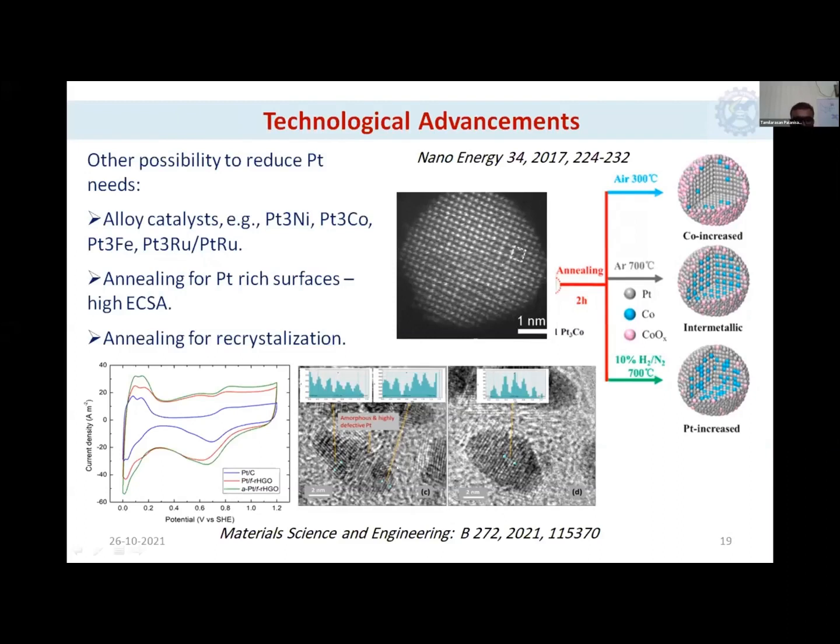But while we anneal in situ, frame by frame, we observed what's happening to the particle. It actually turns into a single domain particle. Okay, it has a single crystallite. But if you see here, before it has more than two crystallites, one, two, and here you are seeing some amorphous-like space.